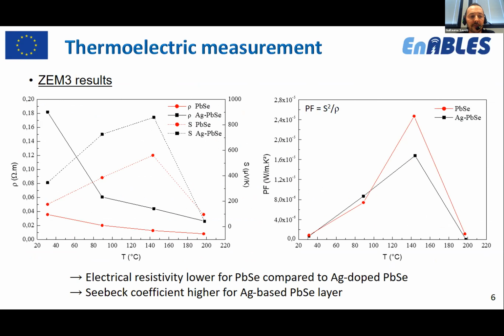In the figure on your left, you have the temperature dependence of the electrical resistivity and the Seebeck coefficient. As you can see, the electrical resistivity is lower for the PbSe layer compared to silver doped PbSe. So it confirms the results obtained by Hall effect. And also, you can see that we obtain a higher Seebeck coefficient for the sample doped with silver compared to PbSe. We can obtain very high Seebeck coefficients up to 850 microvolt per Kelvin, which is a very high value for thermoelectric materials.